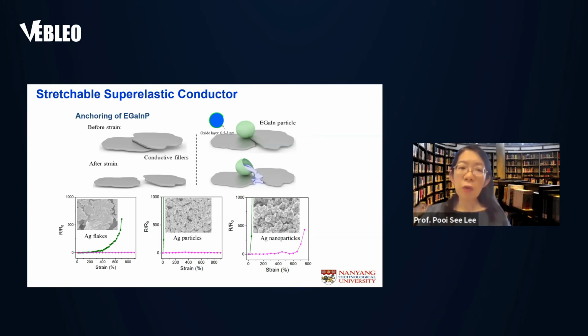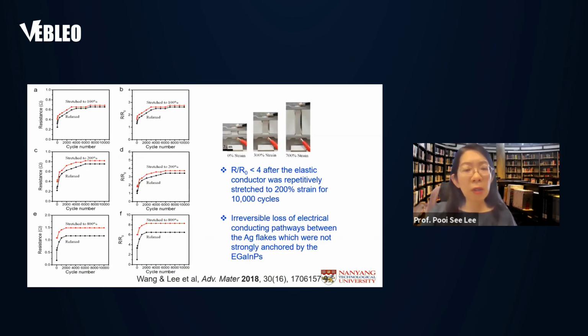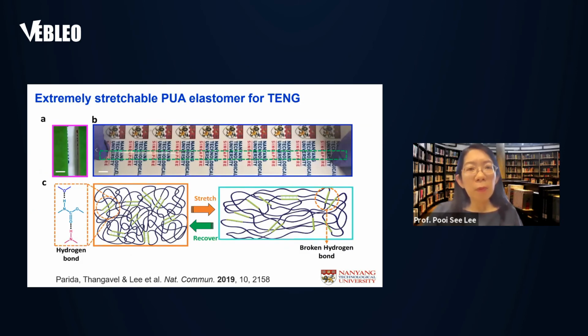It works not just for flakes, but also for silver nanoparticles with the addition of liquid metal. It shows very robust stretchability up to 800% strain, and the resistance increment is rather stable. Although there is a gap between the relaxed state and the strained state, it's very stable. The gap is due to the irreversible loss in the electrically conductive pathway of the silver flakes, which are not anchored by the liquid metal. So this approach allows us to make a highly stretchable device.